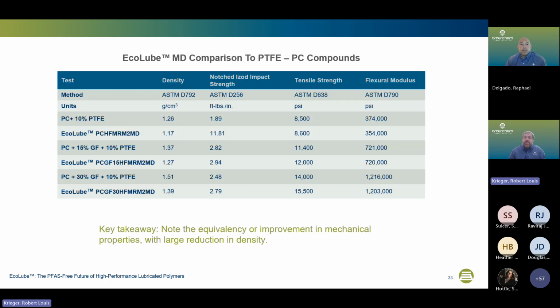And now the corresponding mechanical data in polycarbonate. So again, you see some loss in stiffness and strength going from PTFE to EcoLube, but note the vast improvement in impact, especially in the unfilled polycarbonate. PTFE has this ability to impart a real bad notch sensitivity in polycarbonate, but with our EcoLube offering, you start to get impact numbers closer to unfilled or unmodified polycarbonate, which is about a 16. So we definitely boost the impact in all grades here.